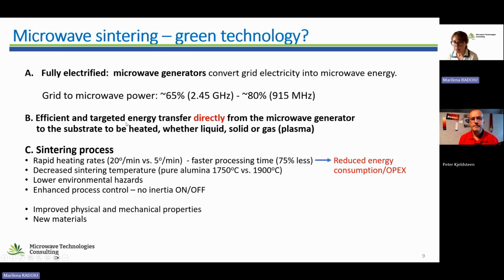But yes, it's true, it's fully electrified with this very high electrical efficiency. But another parameter is exactly what you said, that the energy is targeted directly from the microwave generator to the substrate to be heated. And we gave the example other than ceramics, is liquid, is solid, is gas, I form a plasma, it's straight in there, and it's a known number. I know this number. And if that's a good number, I can do my CapEx, OpEx, and I can do my return on investment. I can do all this model based because I know how much it is. I know how much I need to pay NG or whoever provides my electricity at the end of the month.